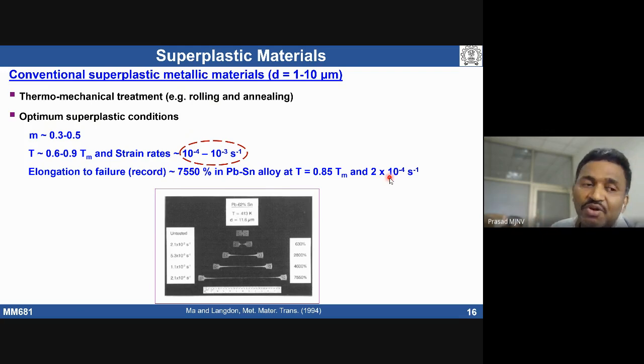If the strain rate is very low, what does it mean? When a strain rate is low, your production rate is low; you cannot produce a large amount of components. If I want to make a car body out of aluminum alloy, and make a large number of components, one has to deform the material at a very fast rate.